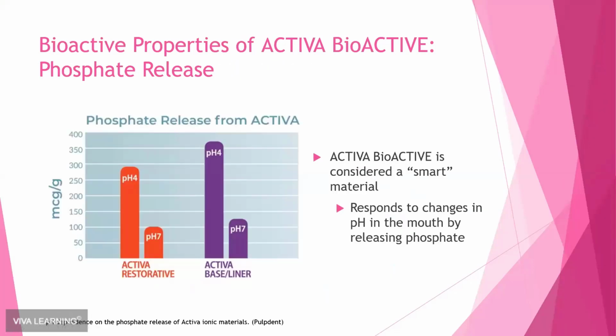All right, and then phosphate release is also really important. This material is considered to be a smart material because it's basically responding as the body is changing. We know that every time a patient drinks anything that's not water or eats anything, it's going to change the pH in their mouth for on average about a half an hour after they're done consuming. So what this graph is showing you is that as the pH is changing in the mouth, the amount of phosphate that's being released changes. At a lower, more acidic pH, this pH 4, we're seeing a higher release of phosphate. And then when the pH is more neutral, pH 7, we're seeing a lower release.